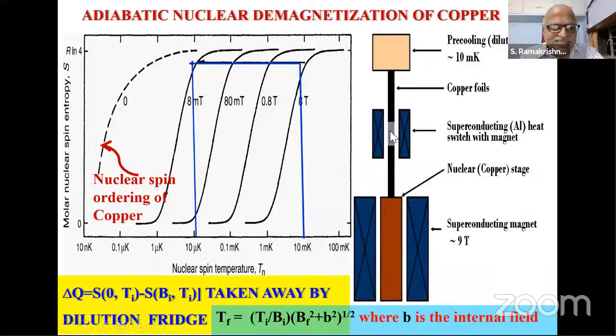So what is this switch? This is, again, an ingenious thing, because for a superconductor, though the electrical conductivity is infinite, its thermal conductivity will become very, very small. So it will be a good electrical conductor but a bad thermal conductor at millikelvin temperatures. So use that as a thermal switch.